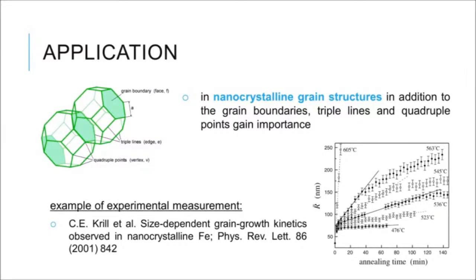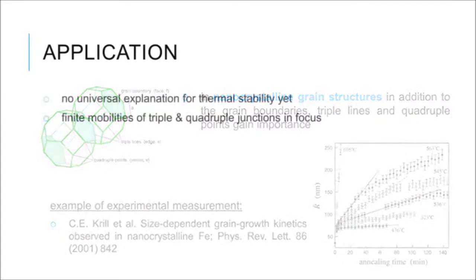This is quite different compared to microcrystalline grain growth in iron, because if you go to larger grain sizes, you will realize that your average radius is a square root function of annealing time. So apparently, in the nanocrystalline size regime, there are changes in the grain growth kinetics.